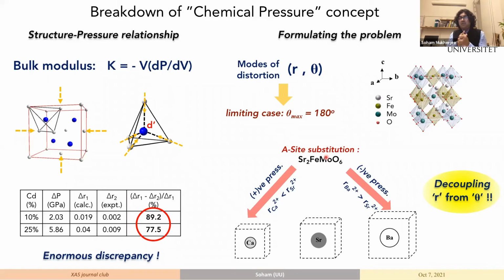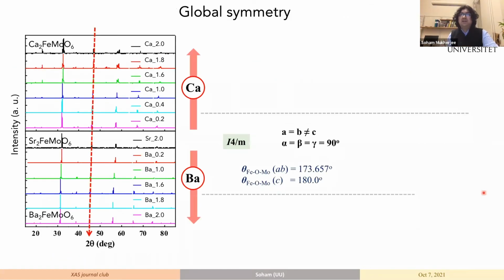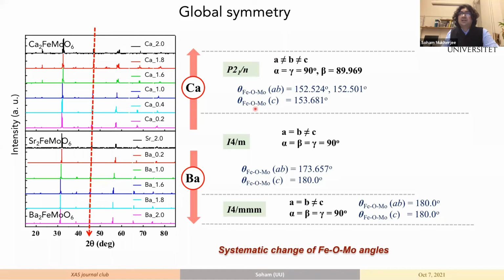The Fe-O-Mo angles are very close to 180. So this is the limiting case of an angle, and an angle cannot increase any farther. So now if you try to increase the pressure, you don't expect any change in the angles. So this will decouple the effect of the change of distance from the angle. With this aim, we went and made a series of samples starting from strontium to barium and calcium. So this explores the positive pressure effect, and this explores the negative chemical pressure effect.